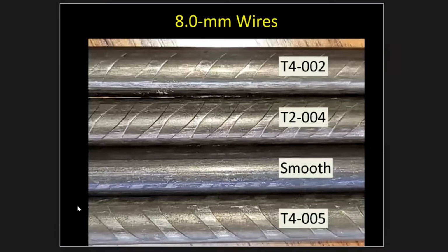So for the 8mm wires, just a picture of this, you can see the T4 style indent. These kind of feather out. There's no edge on this north and south, only an edge in the middle. This is a T4 with a depth of 0.002. Here was a T4 with a depth of 0.005. We had a smooth wire, and this is a T2 style indent. You notice there's a crisp edge where it's essentially full depth top and bottom.